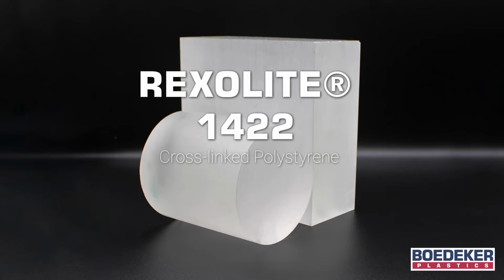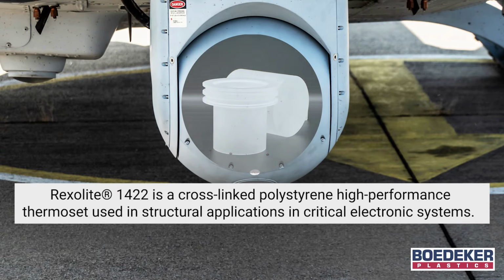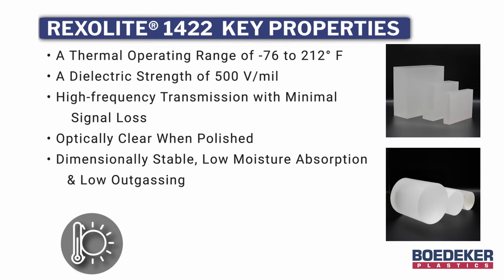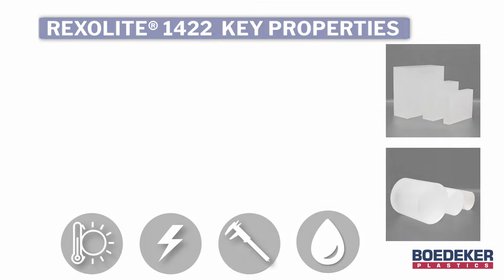Rexolite 1422 is a cross-linked polystyrene high-performance thermoset used in structural applications in critical electronic systems. Key properties include a thermal operating range of -76 to 212 degrees Fahrenheit, a dielectric strength of 500 volts per mil, high-frequency transmission with minimal signal loss, optically clear when polished, dimensionally stable, low moisture absorption, and low outgassing.